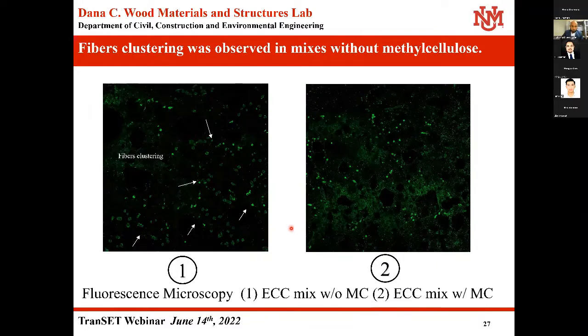We also did the fluorescence microscopy analysis to confirm the dispersion of fiber with the addition of MC in the mix. For standard ECC mix, as you can see, there was fiber clustering in the mix, and a similar thing was observed during the mixing process. But with the addition of MC in the mix, the fiber was uniformly distributed over the mix, and the clustering phenomenon was eliminated.